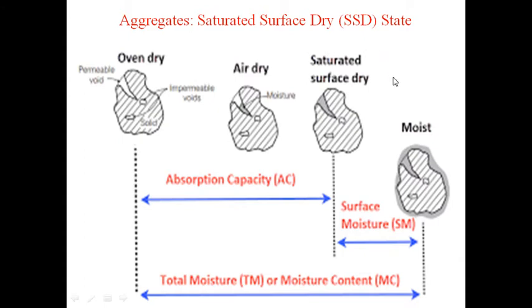What we are interested in is the saturated surface dry condition: the surface of the aggregate is completely dry but all the pores inside are fully filled with water — that is 100% saturation. The advantage of using SSD aggregates in concrete is that when incorporated into the concrete mass, they neither absorb water from the mix nor give out water during mixing, so no water correction for water absorption or moisture content is needed. We can keep sand and coarse aggregate under water for 24 hours, then take them out and make the surface dry, so pores inside are filled but the surface is dry.